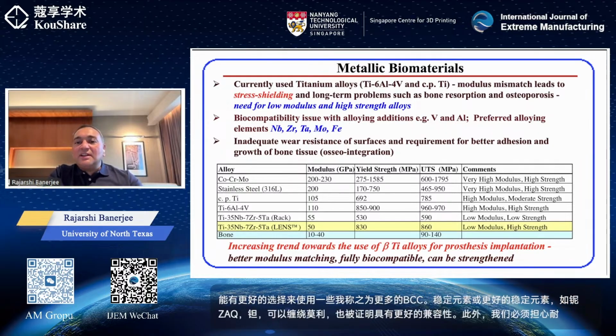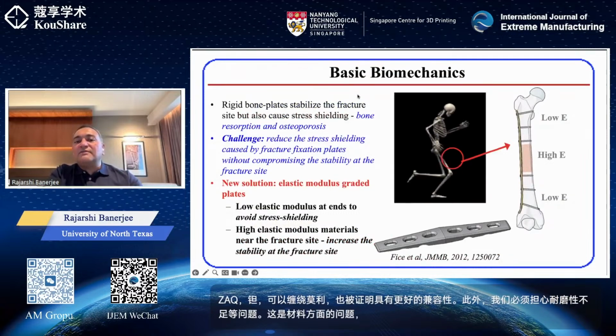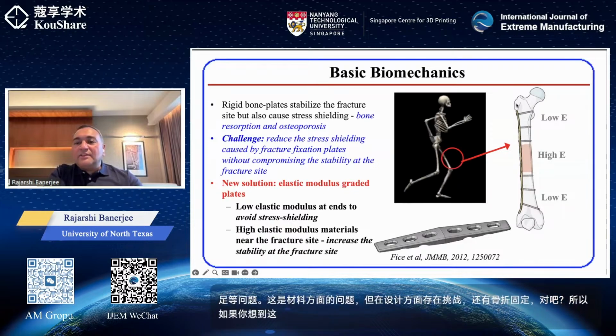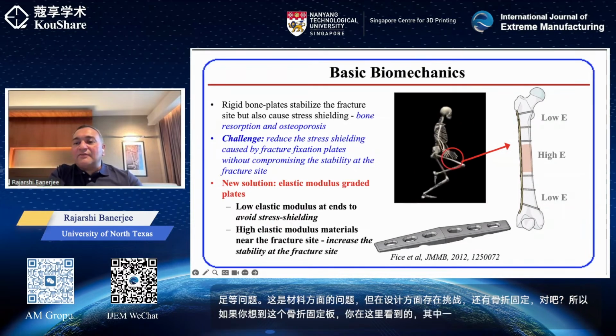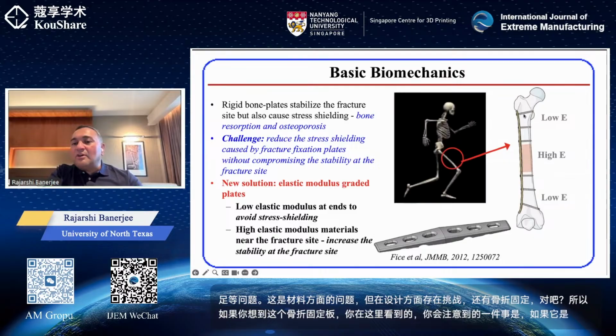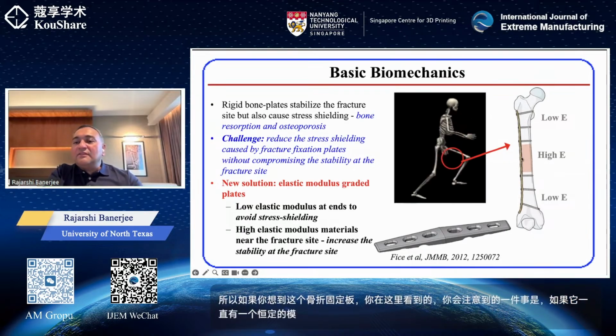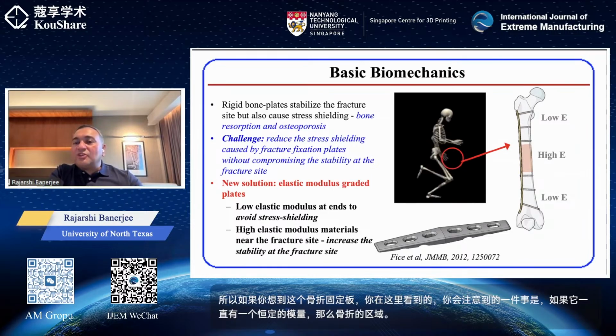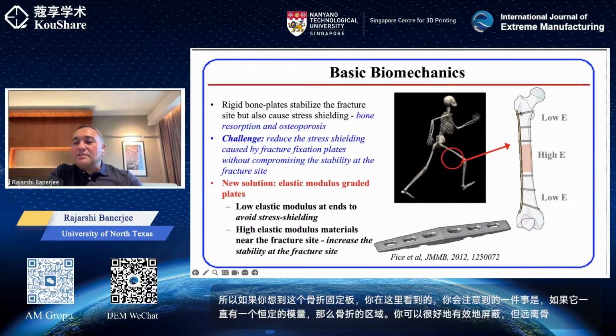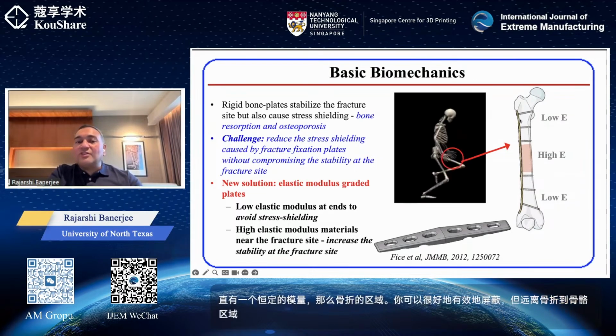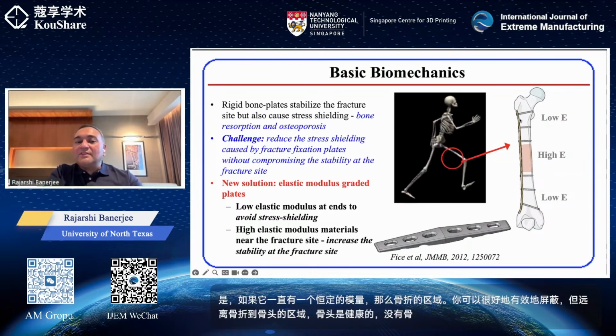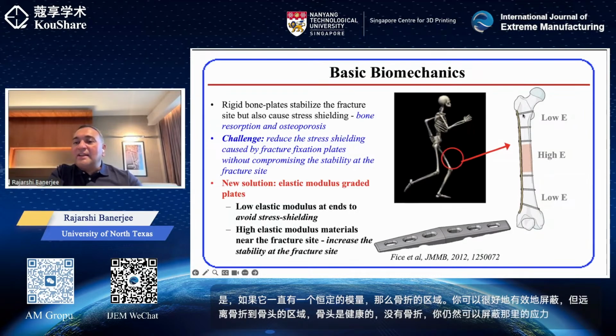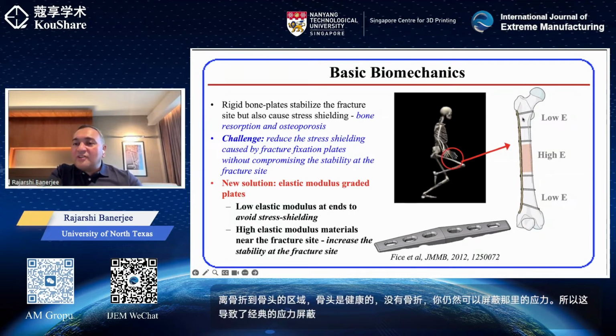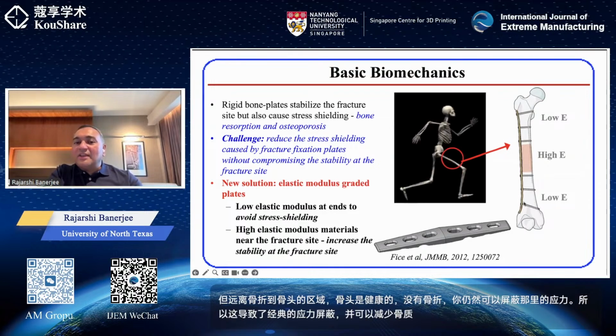But there's a challenge in terms of the design also of a fracture fixation plate. If you think of this fracture fixation plate, which you see here, one of the things you will notice is that if it's got a constant modulus all the way through, then the region of the fracture, you are effectively nicely shielding. But far away from the fracture too, in the regions where the bone is healthy and there is no fracture, you're still shielding the stress. So this results in the classic stress shielding and can lead to osteoporosis or reduction in bone thickness in these regions. And that's a big challenge.